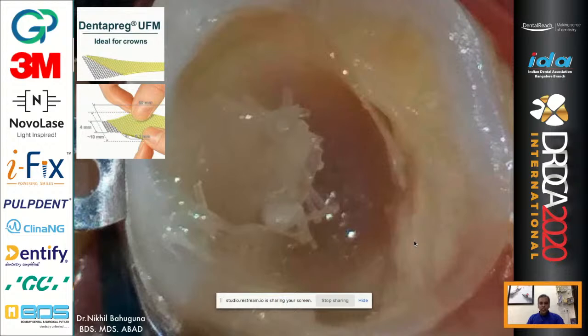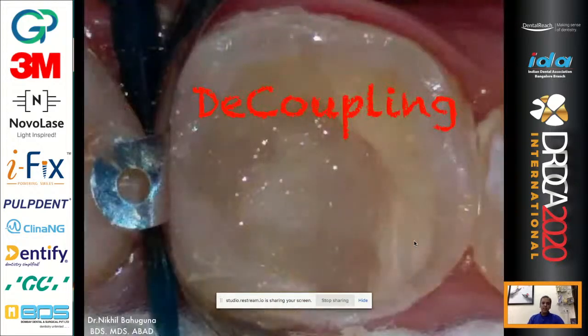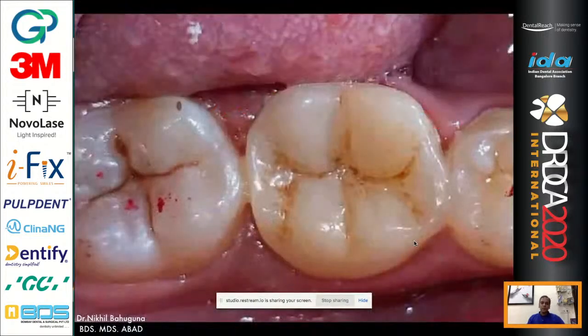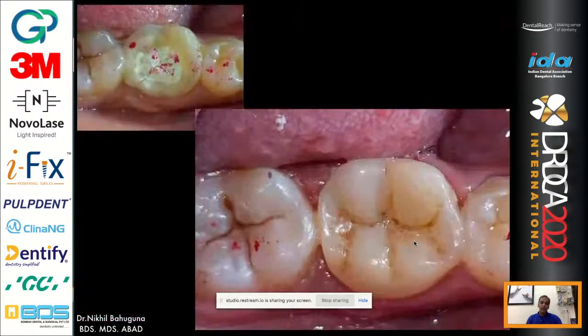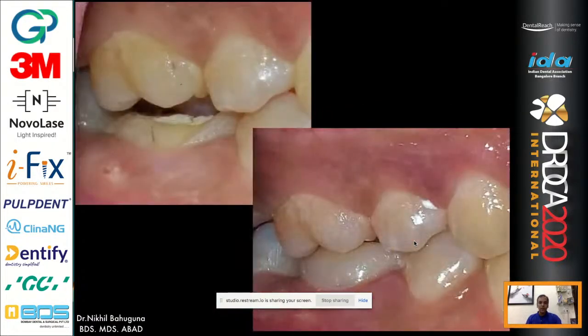With the base with SDR, I incorporate my mesh. This is where I place my mesh. That's exactly what I mean by decoupling. My mesh is completely incorporated into the flowable now. And now when I put the subsequent dentine flowables, the elasticity of the mesh is going to make sure that my bottom layer doesn't pull up. And that's how I built it up with enamel. The patient was fairly happy. The orthodontist was fairly satisfied with the results because that's the kind of occlusion we gave them with a direct build-up.